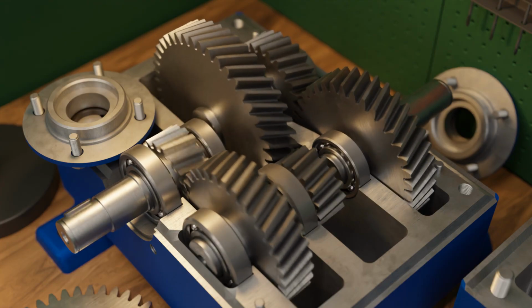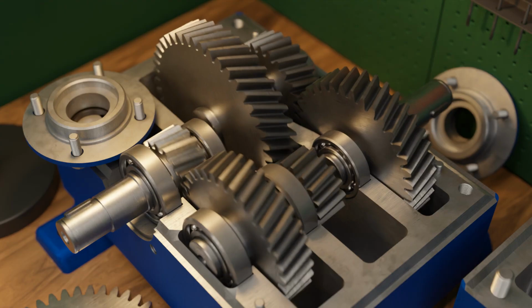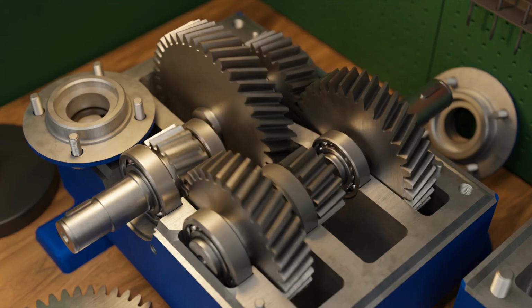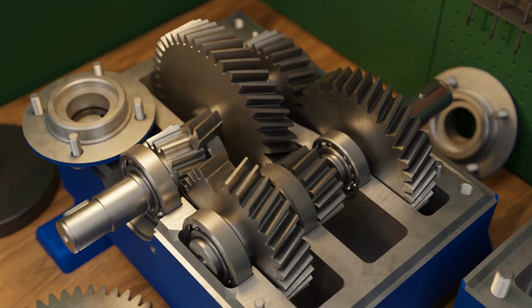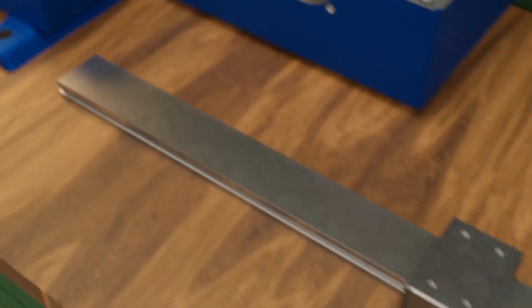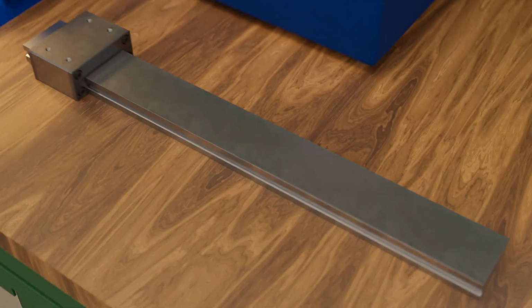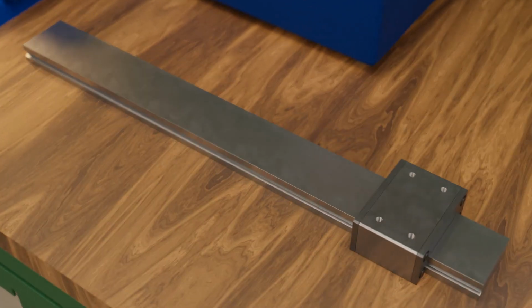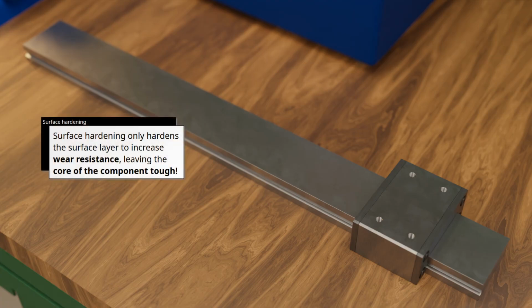However, the disadvantage is the reduction in toughness and embrittlement of the steel, which can lead to unpredictable material failure. For this reason, it is necessary to harden only the surface of a component so that the core retains its toughness. This is known as surface hardening. Typical examples of surface hardening are gears or guide rails. However, crankshafts or camshafts are also usually surface hardened after quenching and tempering. So note, surface hardening only hardens the surface layer to increase wear resistance, leaving the core of the component tough.